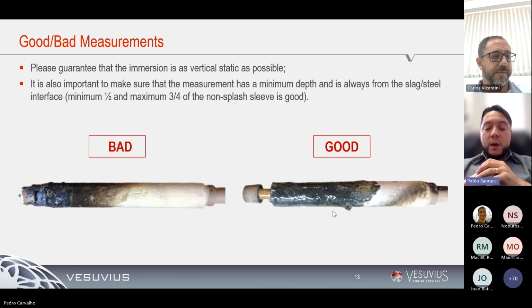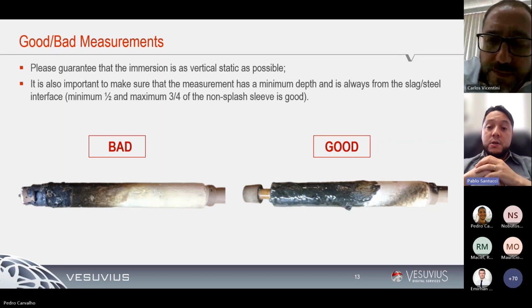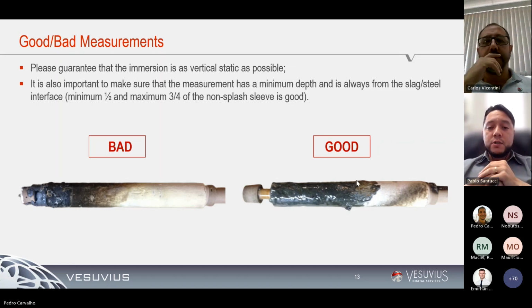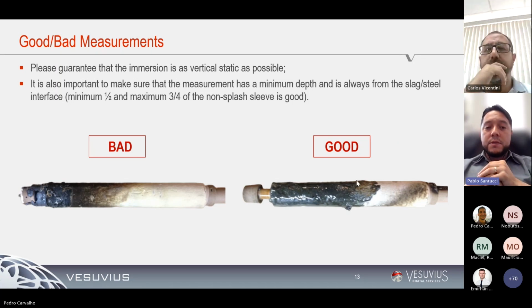One of the good practices recommended from Vesuvius side is to guarantee a perfect immersion and angle for the same immersion. To make a long story short, the optimum immersion procedure would be a probe being immersed inside of the steel as vertical as possible, and also having an immersion depth around half of our non-splash sleeve until max 3/4 of the same reference. So that can be considered a good immersion depth and angle. That can prevent many problems during the immersion and avoid a false reading during the measurement.